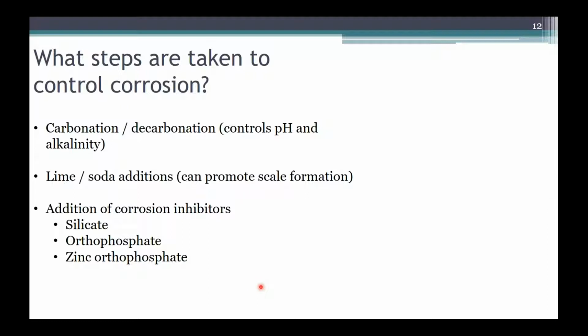I saw a study recently looking at the United Kingdom saying that upwards of 90% of the drinking water facilities there were using orthophosphate as a corrosion inhibitor. And the recommended dosages of phosphate are actually quite high. So they're in the range of 1 to 3 milligrams per liter of phosphate throughout the system. And I'll come back to this a bit later.